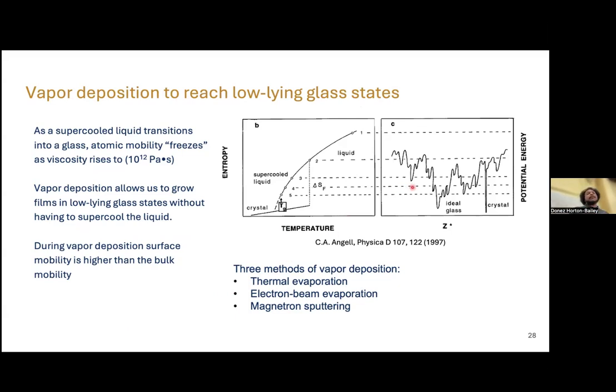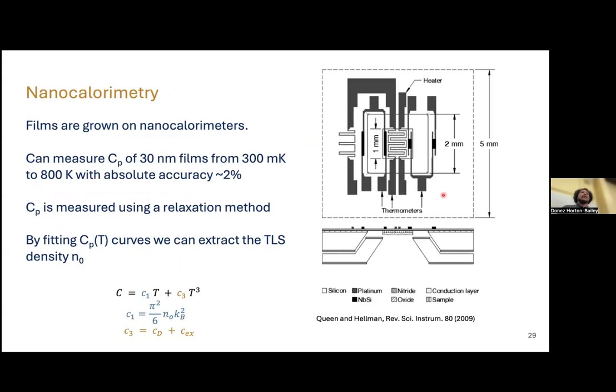The reason why I use vapor deposition is with liquid quenching, I mentioned that we have all these states, all these glassy states. Liquid quenching tends to get you stuck on one of these higher states, these higher entropy states. Notice at this level, there are a lot of states available, but as you go down in the entropy, you also go down in this energy level and there's fewer states available. And vapor deposition allows us to directly grow films that are in one of these lower lying states, which is closer to what we're looking for in low TLS materials.